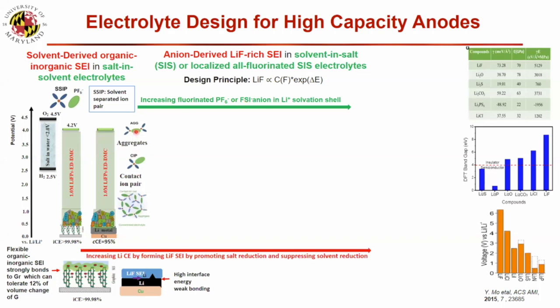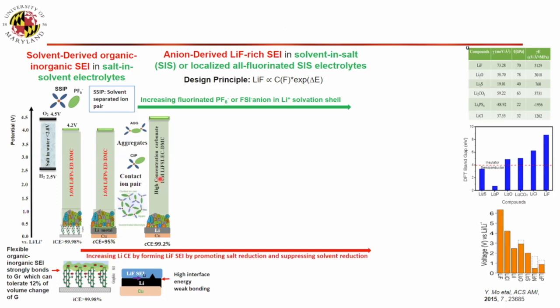And if we put a lot of salt there, they can form CIP and AGG, meaning when lithium moves to the anode side it brings more anion. So the anion has more opportunity to reduce, and they can form lithium fluoride. PNNL also did a lot of work on this, using carbonate with a lot of salt, and they really can increase the efficiency to 99.2. But when we put a lot of salt there, viscosity is high, and then we think we can reduce the viscosity by using a diluent.